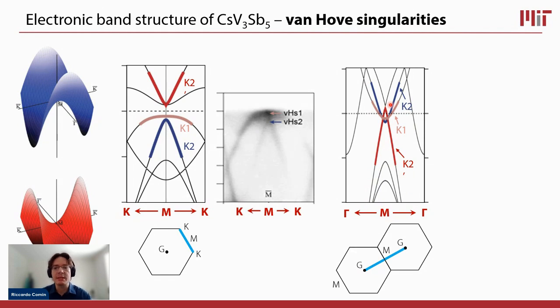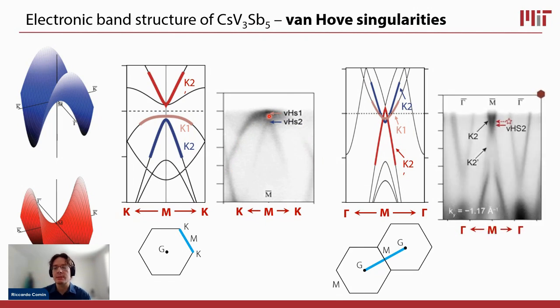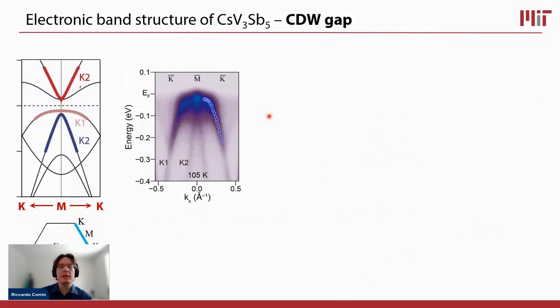We can map these out in great detail with angle resolved photoemission. We can see these bands as a function of momentum and as a function of energy. We can see this band top, which is this locally flat dispersion that forms a Van Hove singularity. The really intriguing thing is that at high temperature, above the charge density wave transition, these bands have this Van Hove singularity almost perfectly at the Fermi energy, which is where we expect the system to become unstable towards symmetry breaking.